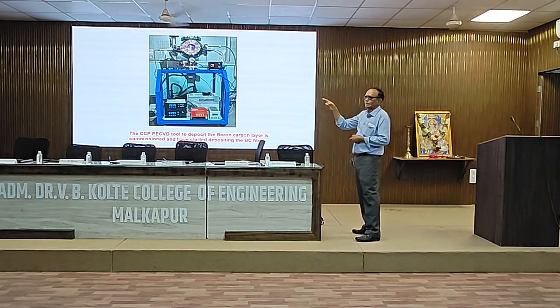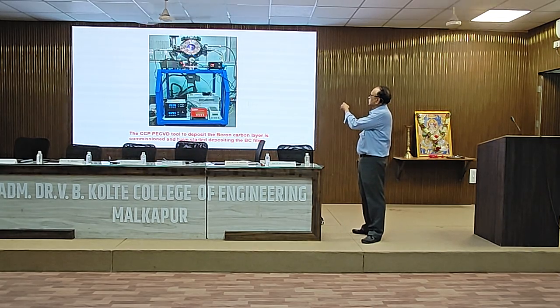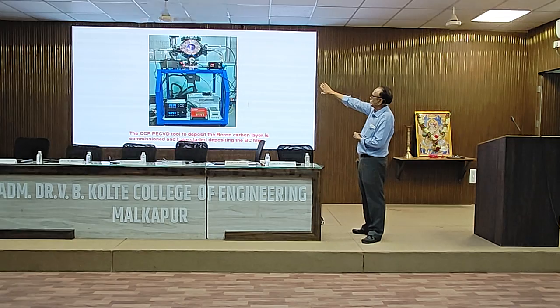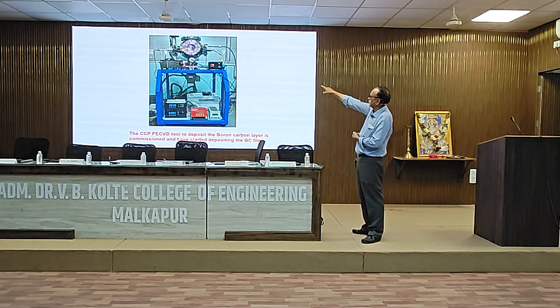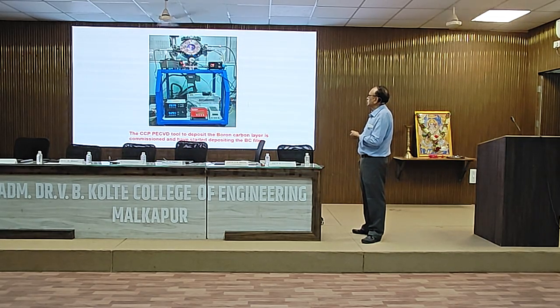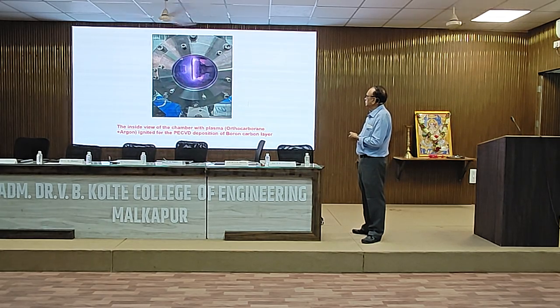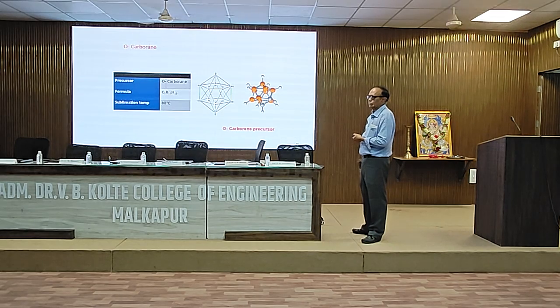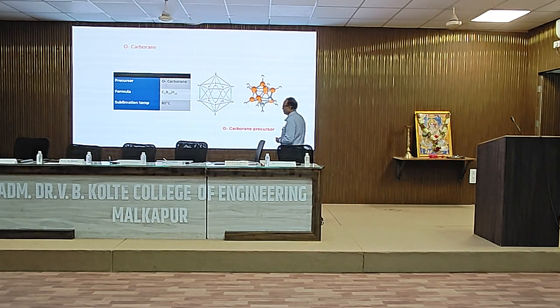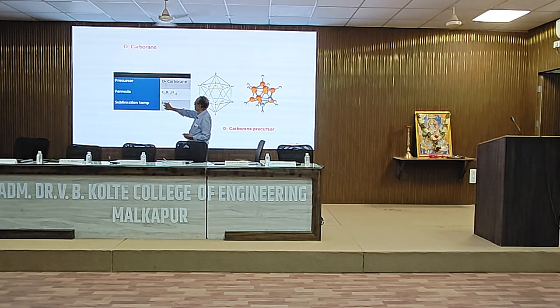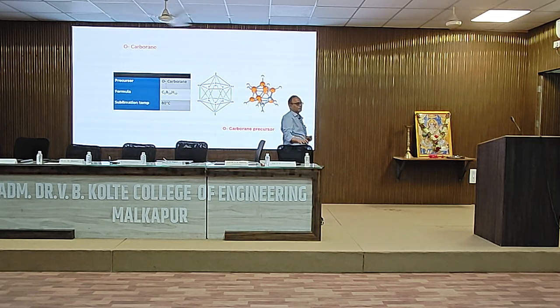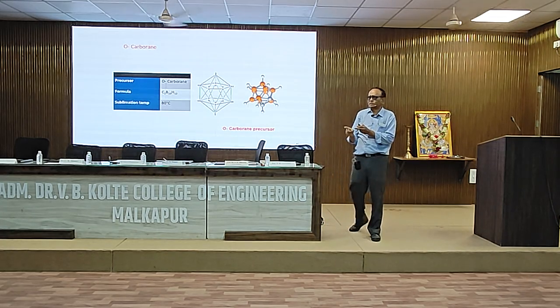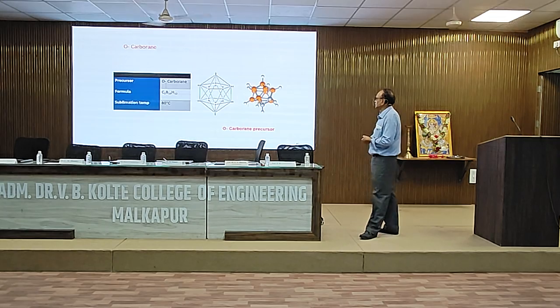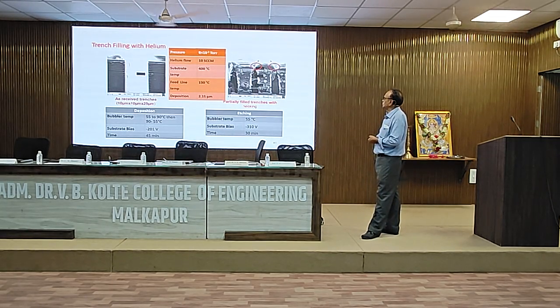We use a radio frequency plasma, which I have discussed with you. This is the plasma chamber in which those electrodes are there, and onto which we mount that p-i-n junction assembly. Then the precursor is decomposed by the plasma medium, and it gets deposited there. This is the process that is going on. This is the precursor that we use, orthocarborane, a giant organic molecule, C2B10H12, with a sublimation temperature of 80 degrees centigrade. When it sublimes and decomposes in the plasma, you get boron-containing radicals, carbon, and so on. So what you deposit is a boron carbon containing phase. So this work is going on.